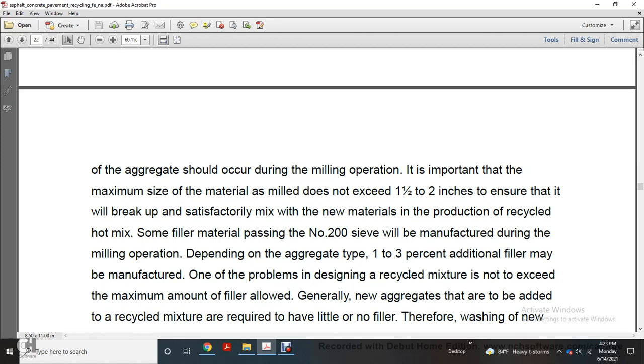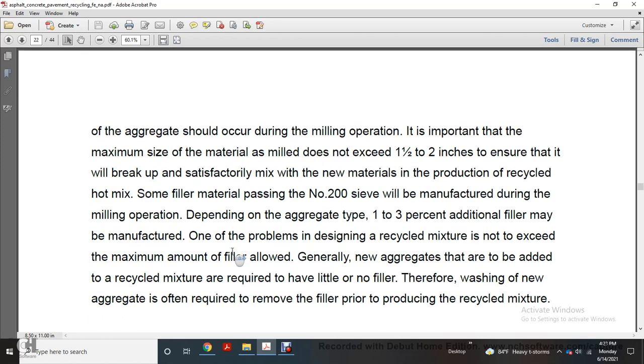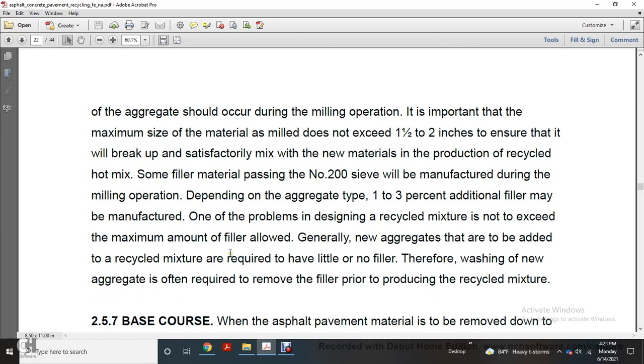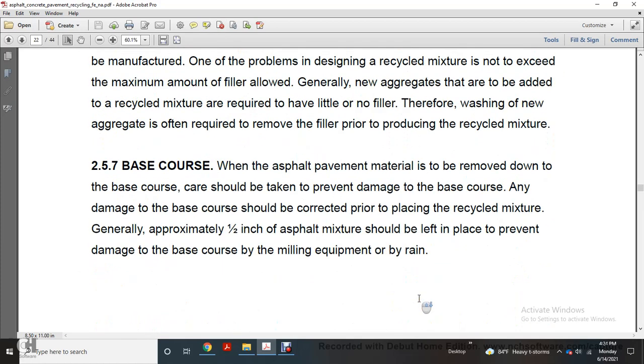New materials for producing recycled hot mix: some of the filler material passing the number 200 sieve is manufactured during the milling operation, depending on the aggregate type. One to 3% of additional filler is manufactured. One of the problems in designing the recycled mixture is not to exceed the maximum amount of filler allowed. Generally, new aggregates added to the recycled mixture require little or no filler. Therefore, washing new aggregates is often required to remove filler prior to producing the mixture.